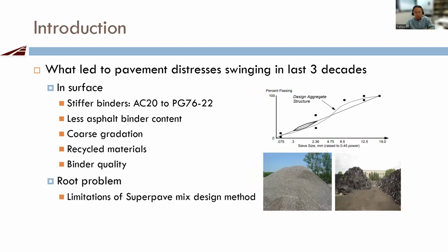So what really led to different types of pavement distress, swinging from rutting to cracking? What's really led to those issues? On the surface, people may say it's the binder. We switched binder from AC20 to PG76-22. The binder becomes stiffer, so we eliminate the rutting issue, but the binder is too stiff and causes a cracking issue. Another thing people may say, oh, well, binder content is much less than 30 years ago. That causes cracking issues. That could be the reason.